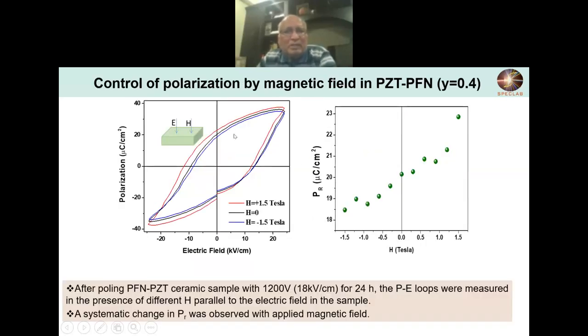We wanted to know if there is any magnetoelectric coupling occurring in that one. At that time, we didn't have any other tool, so we decided to look at only the ferroelectric loop and apply the magnetic field. Not very high yet; we had at that time 1.5 Tesla. And you can see that in the ferroelectric loop the remnant polarization changes. We have plotted that change here. That change clearly indicates that a magnetic field can change the polarization.